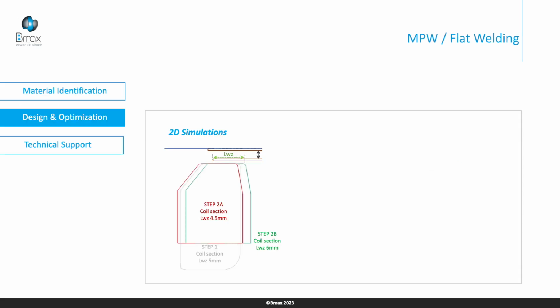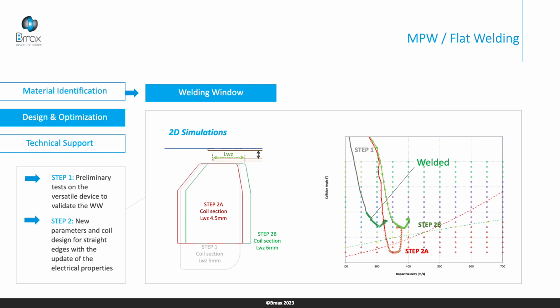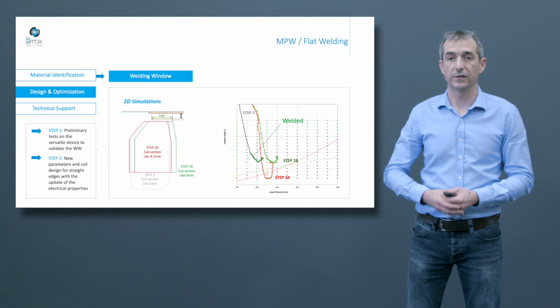After, we perform 2D simulations. Step one consists of using an existing setup to validate the welding window. We perform micrography to check if the welding window is respected. And as you can see, the green line shows the length of the welded zone, and we are in good compliance with what we expect.